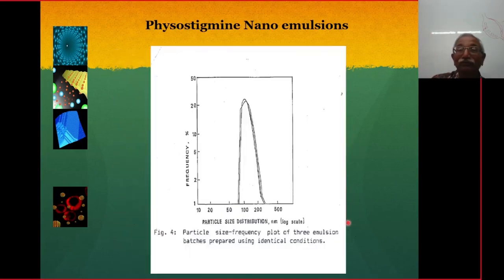So this was our nanoemulsion particle size distribution. You will find that it was a very uniform nanoemulsion. The particle size was ranging between 80 and a maximum of 250 nanometers, with an average of 120 nanometers. So it was a hardcore, nice nanoemulsion reproduction. I do it in my lab even now. Our nanoemulsions are very reproducible, and you can incorporate the things.